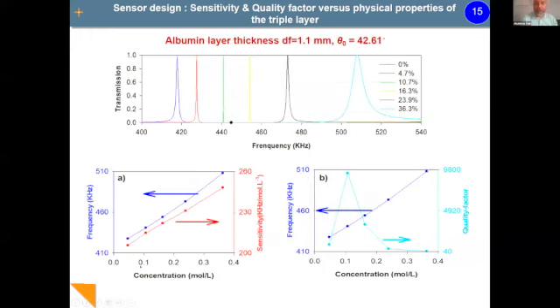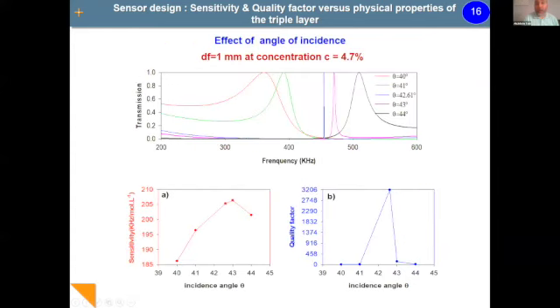We can also fix the layer and the angle of incidence and change the concentration. It's exactly the same parameter. We can move a lot of parameters. And finally, we can also change the angle of incidence and put the resonance where we want, for example to target a large dynamic range of concentration. We can sense both low concentration and high concentration, because the position of the bound state can be controlled in several ways.